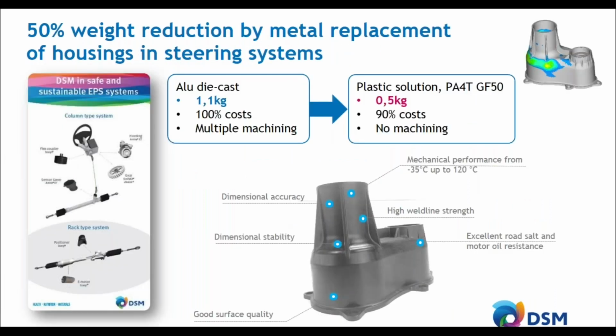So let's take one of the case studies. If you have an electronic power steering system in your car, you actually have two different types, but they all contain a housing, and that housing is mostly in aluminum die cast. They weigh around 1.1 kilogram. Mostly multiple machining actions are required to meet the full dimensions. We are able to replace that with a polyamide 4T with 50% of glass, reducing 50% of the weight and around 90% of the costs. Typically, these parts have to perform from minus 35 degrees C up to 120 degrees C, need a very high dimensional accuracy and stability, good surface quality, and of course they have to be able to deal with the road salt. So how would a design like that look like?